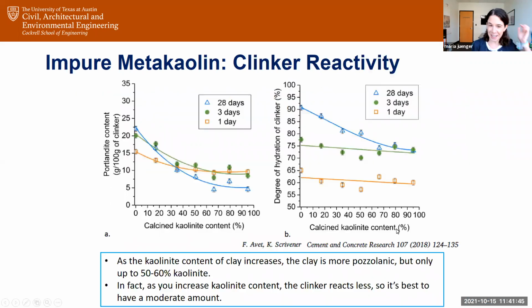Yeah. Okay. The other thing that's interesting is if you start using these less pure materials, again, this is counterintuitive. You think you want to use the best, but there's so much literature and data out there that says, let's aim for mediocre. This is an example from a study in Switzerland from 2018 that basically says, as you increase the kaolinite content of a calcined clay, so you increase that amorphous content effectively, you actually decrease the reactivity of the cement itself. So they're competing.